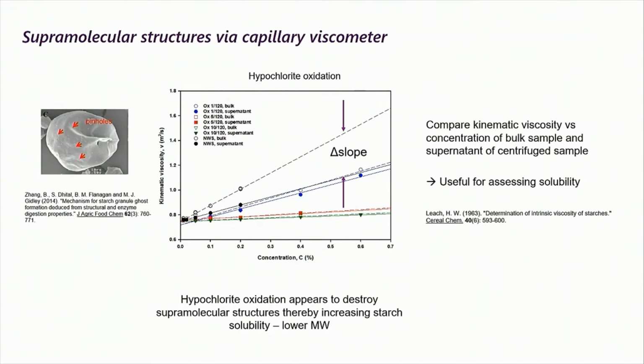You can see that for the hypochlorite oxidized samples, with the blue the 1%, red the 5, and the green the 10, those before and after centrifugation slopes are really quite close together. That indicates that you've got much more of a homogeneous solution. So one of the goals, I suppose, of trying to oxidize the starch was trying to improve that solubility, and so this is a way of seeing that that's occurred.